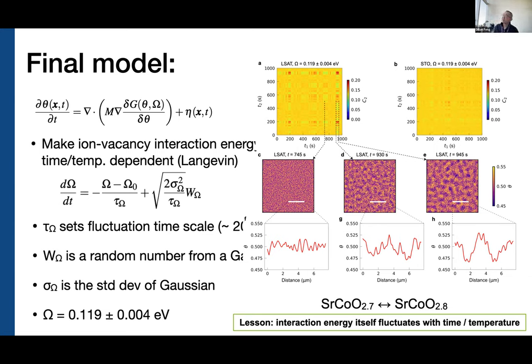From this relatively simple energy model, the theorists at Oak Ridge found that we could explain these two-time correlation maps by assuming that the interaction energy between the oxygen vacancies, ordering the oxygen vacancies, is fluctuating with time and with temperature. Then you can get these timescales.